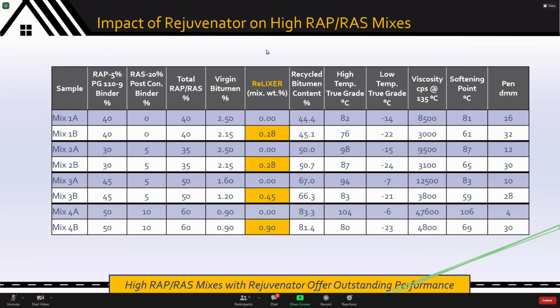As you step from mix 1 to 2 to 3 to 4, what you're increasing is the recycled bitumen content. So for example, in the case of mix 1, it's about 45%. In the case of mix 2, 50, 60, and so on and so forth till 80. As you can see in mix 4, for A, no rejuvenator. For B, with about 1% by weight of ReLIXER rejuvenator. The recycled content in these mixes is about 80%.